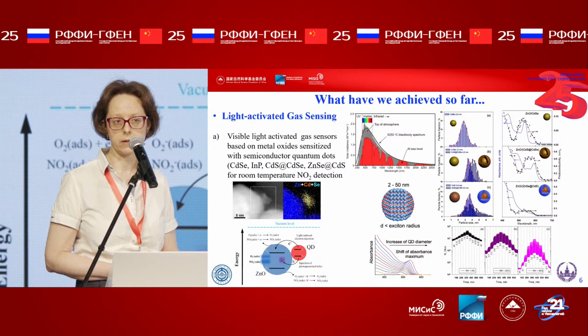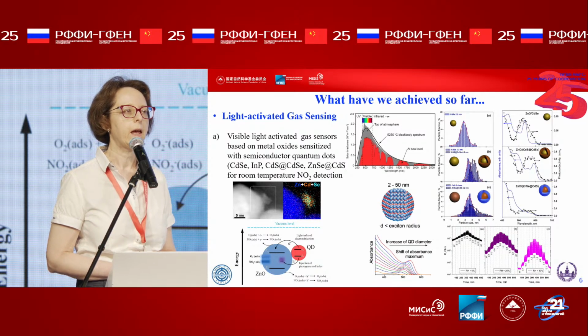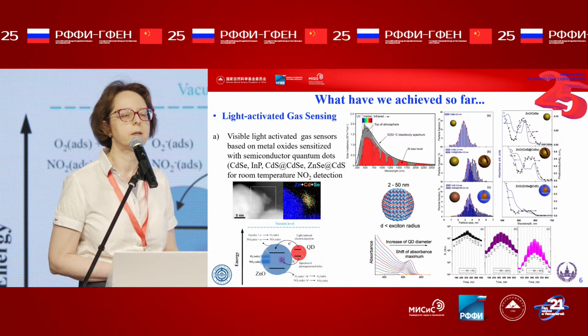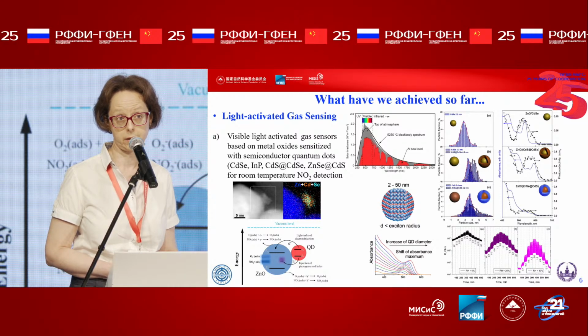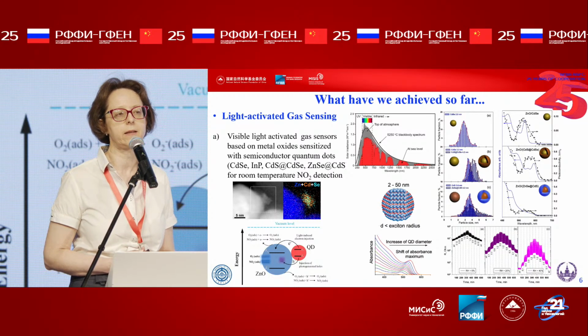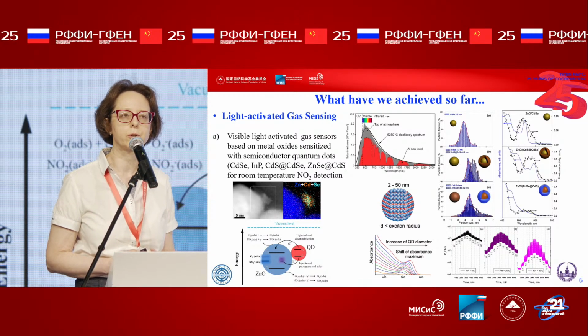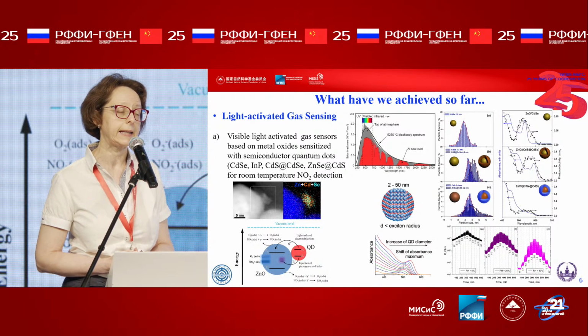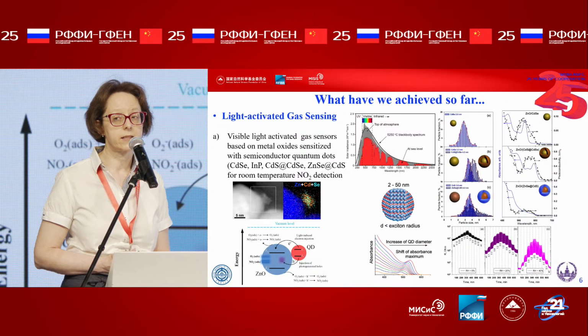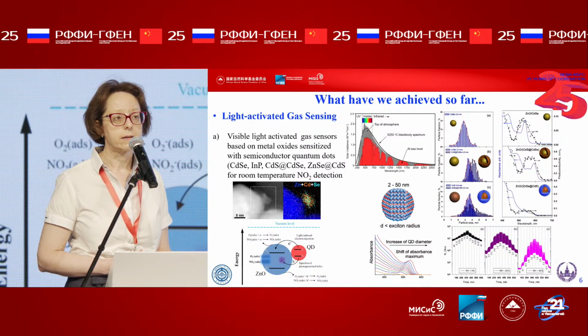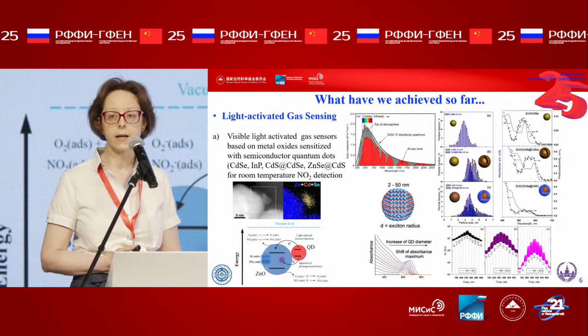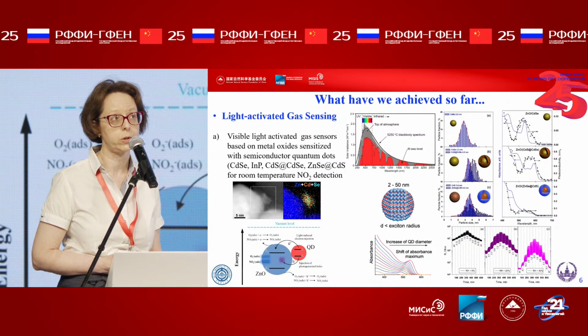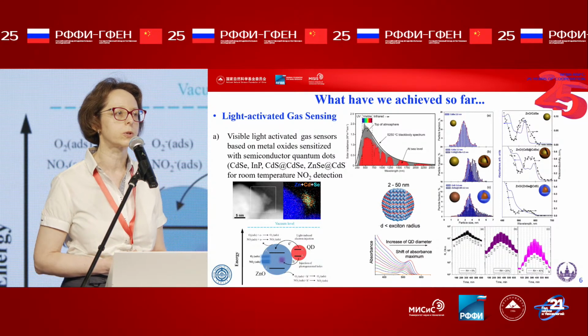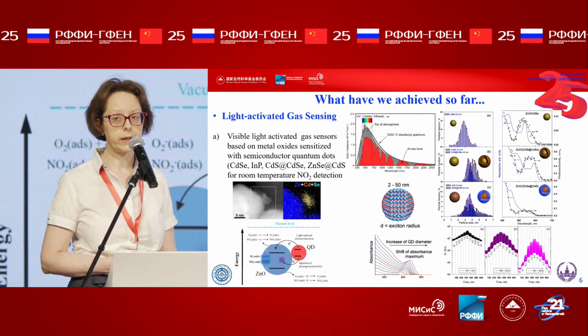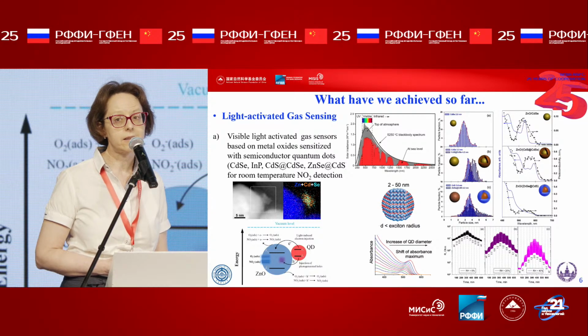Such design of materials allows us to change significantly not only the absorption spectrum of the materials, but also the spectral dependence of photoconductivity. And in this way, we can regulate the properties of these materials depending on the light. And finally, we developed sensors with very high sensitivity and very high selectivity towards oxidizing molecules like nitrogen dioxide and ozone, which are very important environmental gases, and also some biomarkers. And these sensors can work at room temperature without any thermal heating under visible light activation.